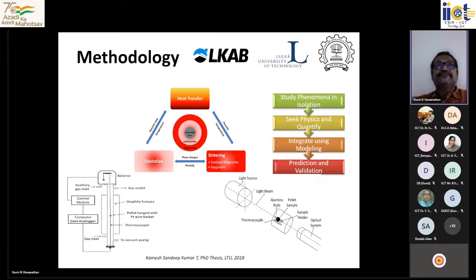One of the ways of knowing how sintering has happened is a very simple technique where you have a light source, you keep a pellet, and you can control the temperature. You take a shadow picture, and you can see how the size decreases as a function of time. Of course, it needs a good amount of optics and image analysis because it's all at a small scale. But once the resolution is good, you can find out how the shrinkage is happening. That way, you have a quantitative, in situ way of measuring how the sintering is happening with time. This is one way we adopted to study sintering.